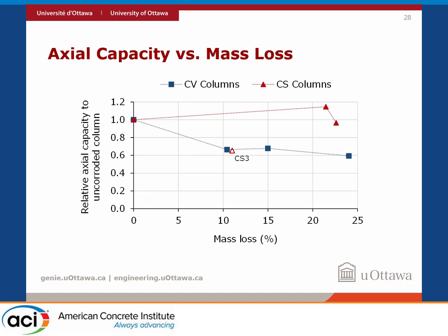And then here you have the relative ratio of the corroded bearing capacity versus the uncorroded columns. And as you can see, the ones that were confined were able to keep their capacity up to the second peak. But those that were unconfined lost between 30 and 40% of the bearing capacity.